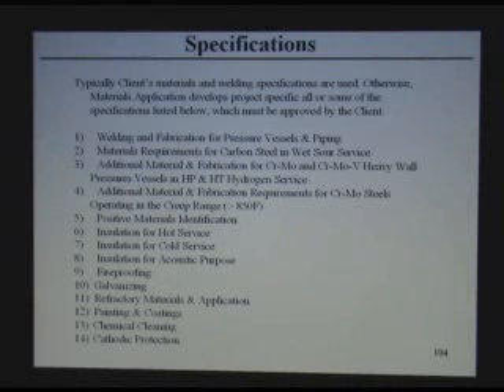We put also material requirements for materials that will be used in the creep range. Actually in the CCR units, which operate above creep range, if you don't specify the proper metallurgy, you end up with creep and cracking due to high temperature operation. We prepare positive material identification. Actually, we have one for that.